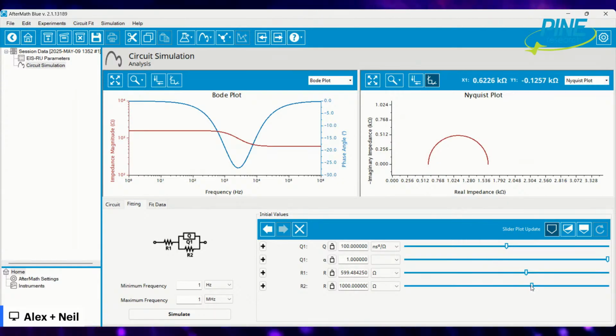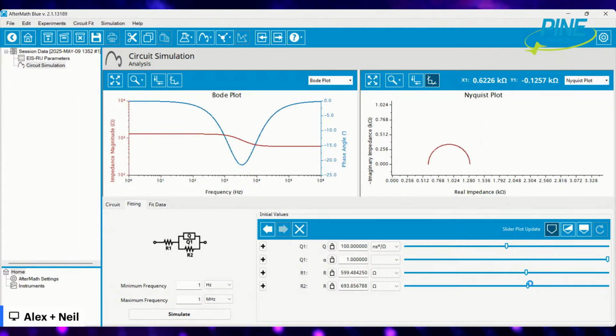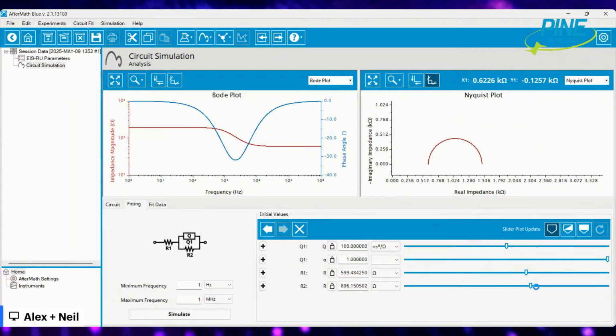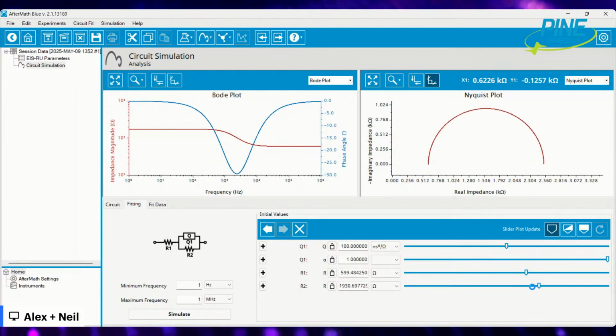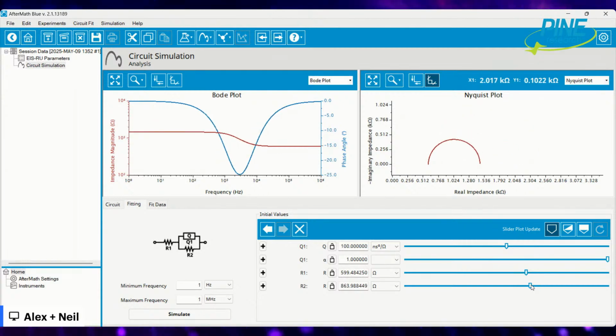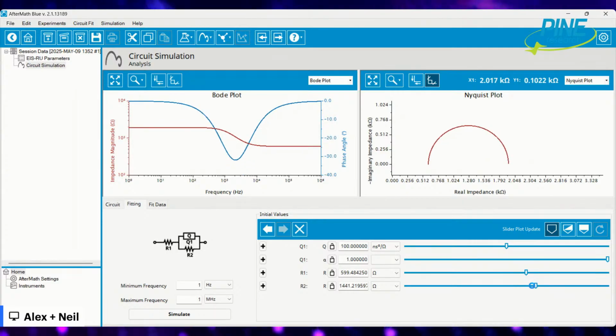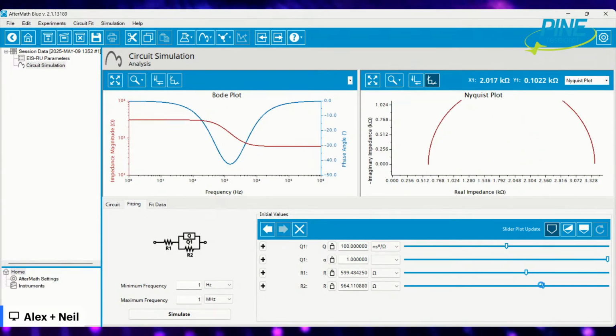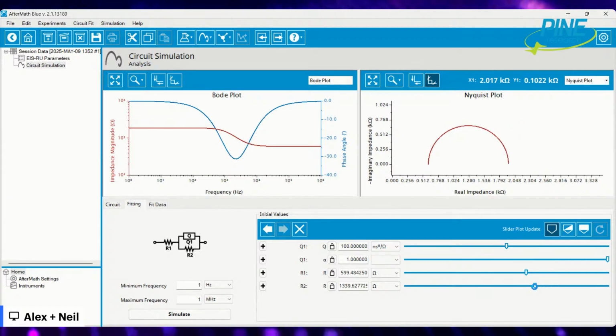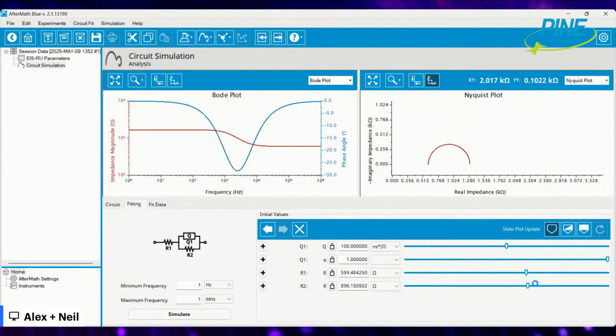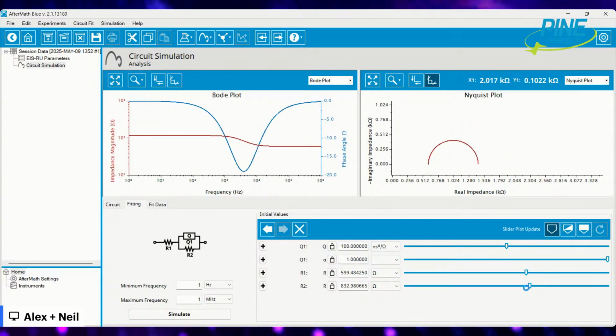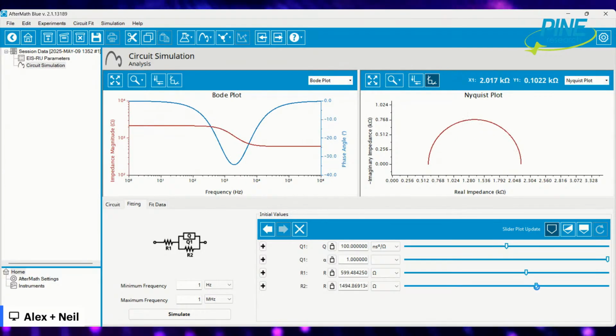And then the charge transfer resistance is the width of the semicircle, very simply. Now, a circuit fitting algorithm, ZSimpWin probably has that. Our software does too. This is just a simulation. I'm not circuit fitting any raw data per se. I could show you that, but I won't get too heavy into that just for interest of time. But you can see as I change the value from small to large, the semicircle grows or shrinks. So very simply, the resistances are actually quite easy to find on a Nyquist plot. The solution resistance is the left intercept, and the width of your semicircle is equivalent to the charge transfer resistance. So that's how you get those directly from a Nyquist plot.